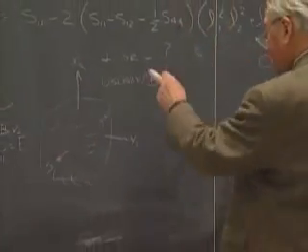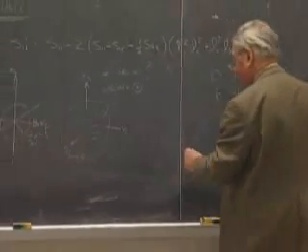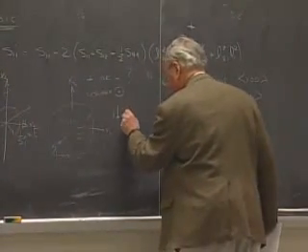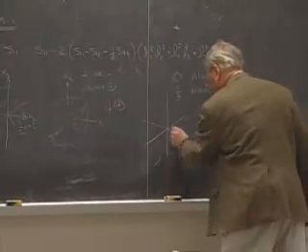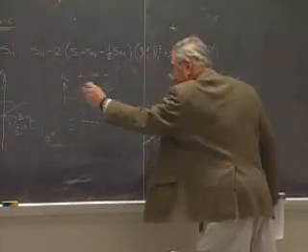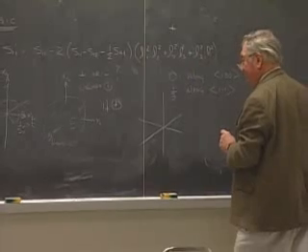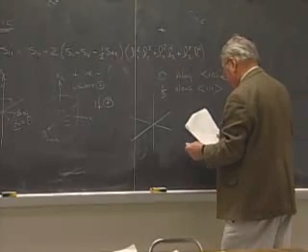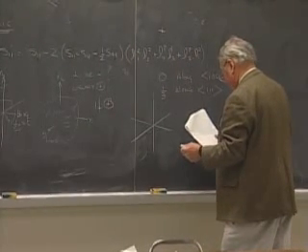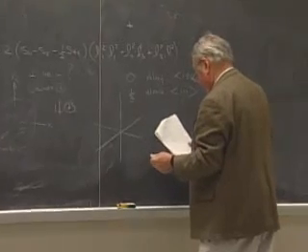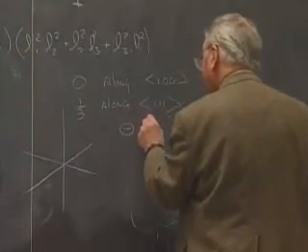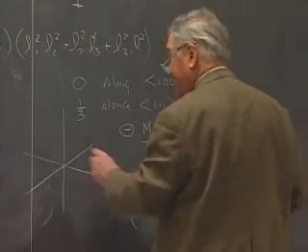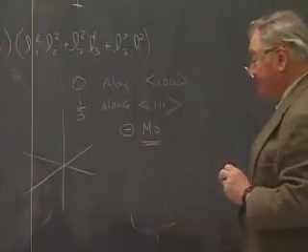If, on the other hand, this term is negative, so this is what you get if it's positive. If it's negative, again, you start with the basic isotropic variation of 1 over S11. If it is negative, and there's one metal, that's molybdenum. Molybdenum has a negative value of these compliances.